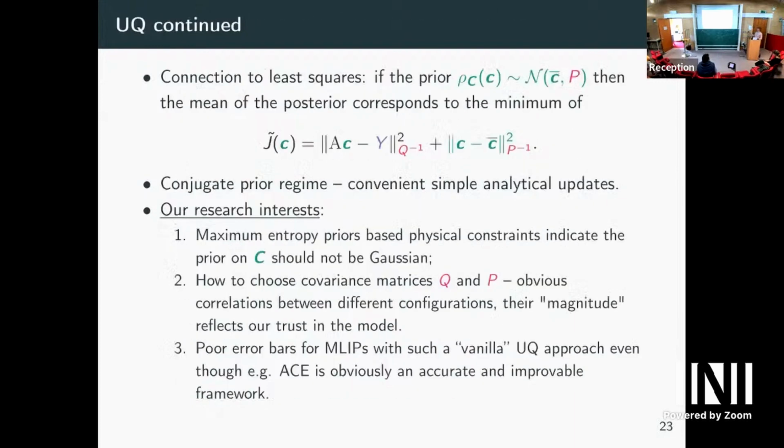So really, if you want to strip away all that complexity, under the hood, these coordinate changes are related to spherical harmonics. And so you can think of all that fitting to quantum mechanical data as a high dimensional equivalent of polynomial approximations by Legendre polynomials, because they are associated with spherical harmonics.